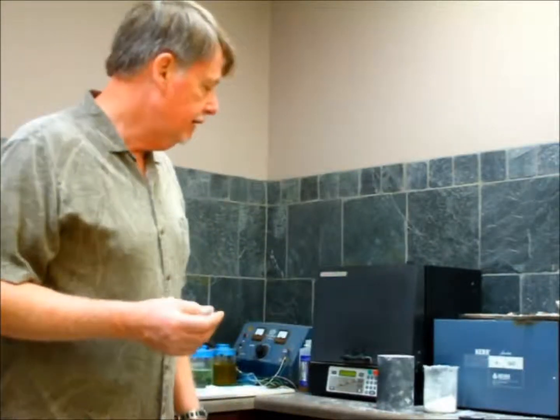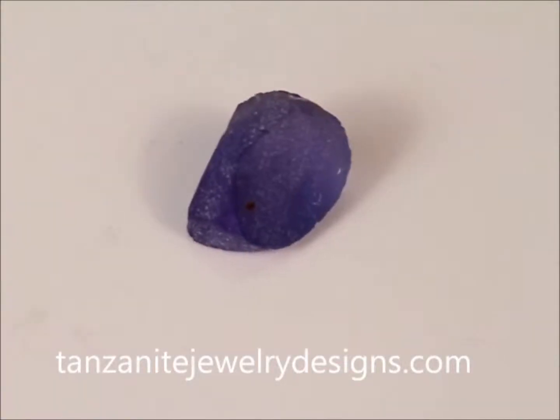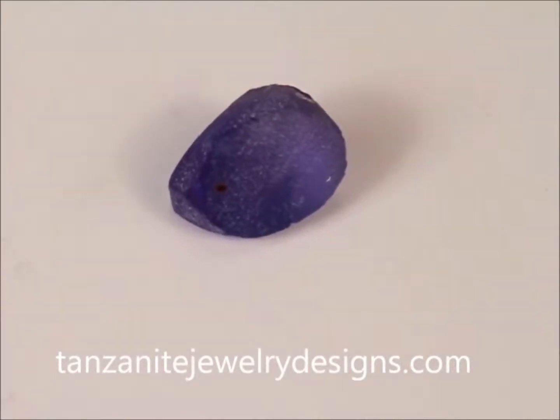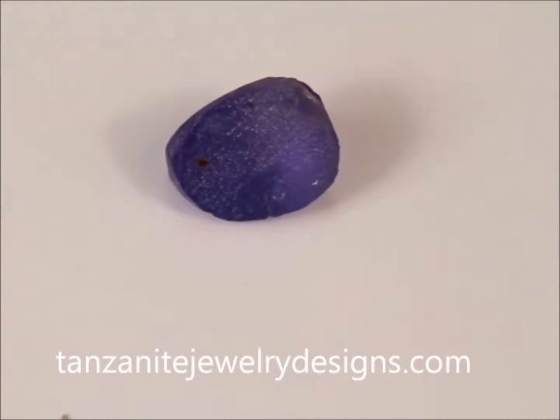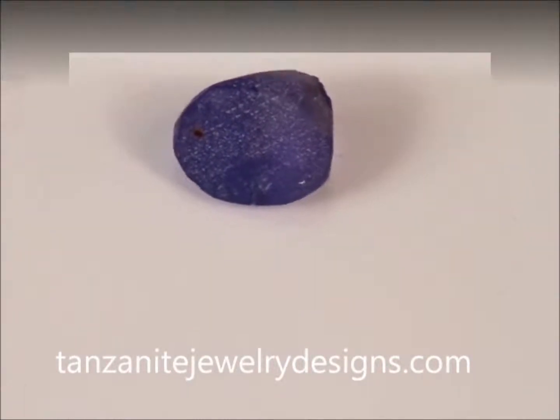To do this we have to heat tanzanite to 1,000 degrees Fahrenheit. It takes about 10 hours. We'll be able to remove this and see what the color of our gem is. Now here's our preformed rough piece of tanzanite once again after treatment at 1,000 degrees Fahrenheit.